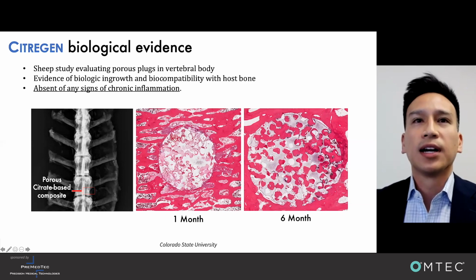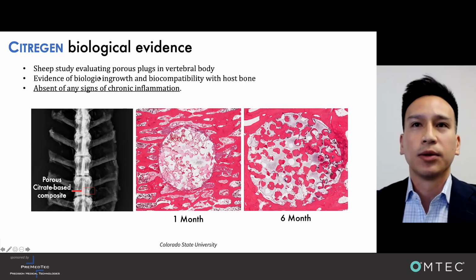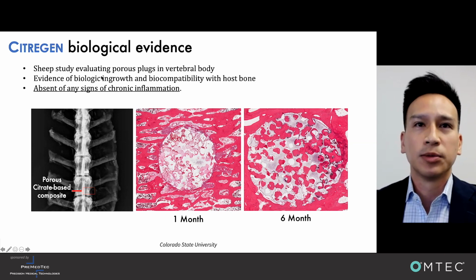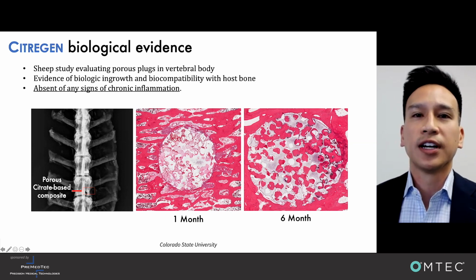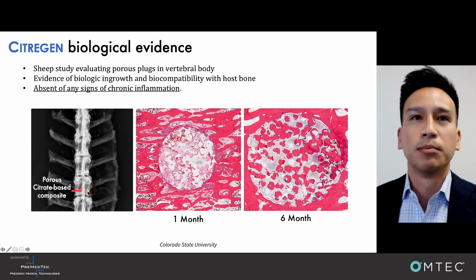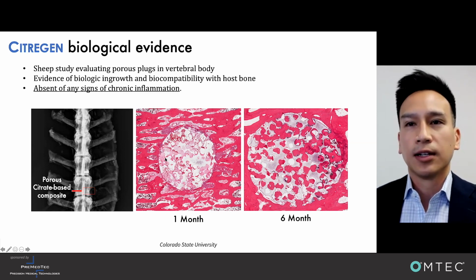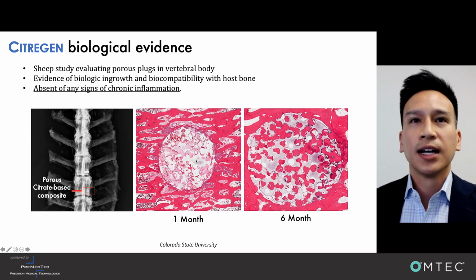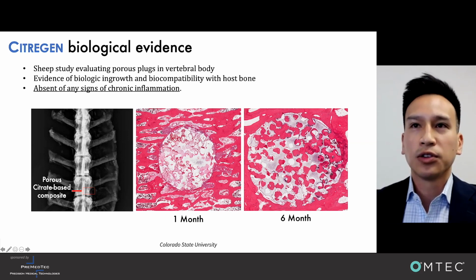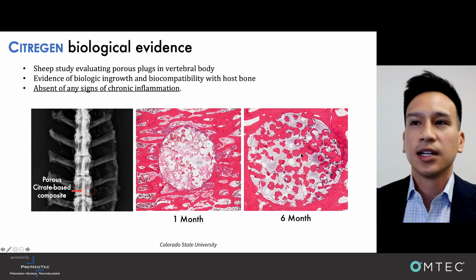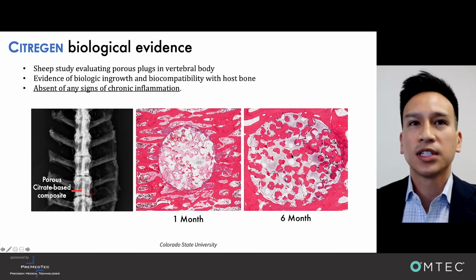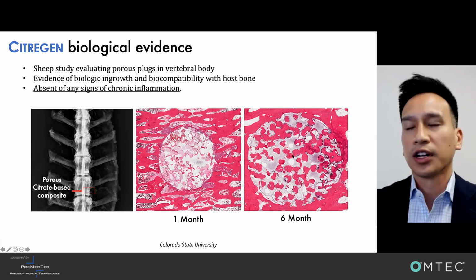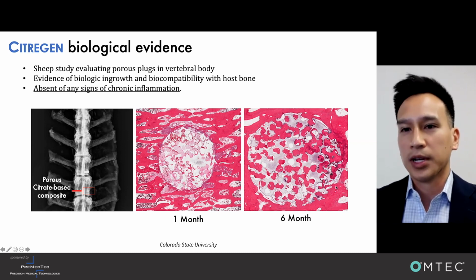Next, we wanted to look at the biological evidence using a sheep study. We looked at porous plugs implanted in the vertebral body. You can see the Citregen material here. It's very faint because the high ceramic content matches the bone density. We looked at 1 month and 6 month histology. We saw evidence of biological ingrowth and biocompatibility. By 6 months, tissue had infiltrated the interior of the pores, and it was absent of any signs of chronic inflammation or any fibrous tissue formation.